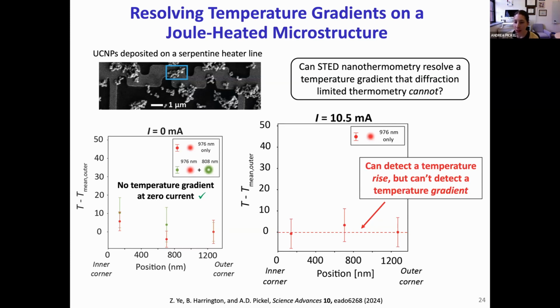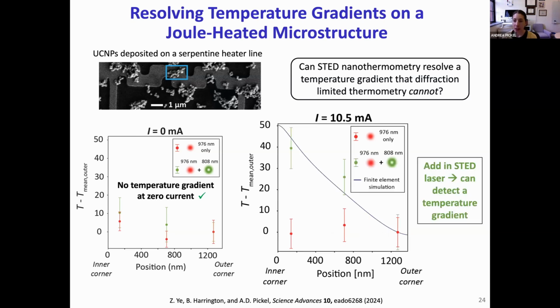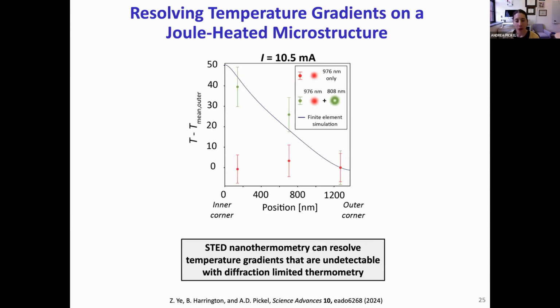But now, if we add in our donut-shaped beam and perform STED measurements at the exact same points, we do indeed resolve a temperature gradient with a higher temperature measured at the inner corner than at the outer corner, exactly as we expect. And this measured temperature gradient also agrees reasonably well with the prediction from our finite element simulation. So there's, of course, more work remaining in terms of developing STED nanothermometry into a practical nanoscale temperature mapping technique, but we're excited about the successes that we've had so far, including this demonstration that STED can resolve a temperature gradient that can't be observed with diffraction-limited measurements.